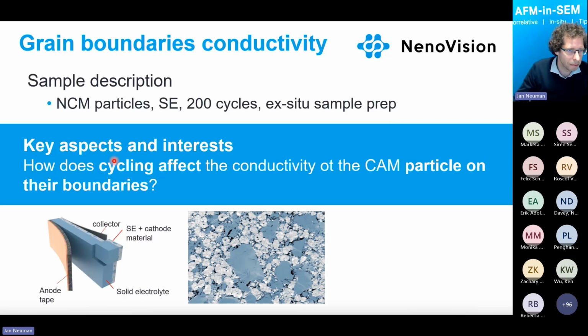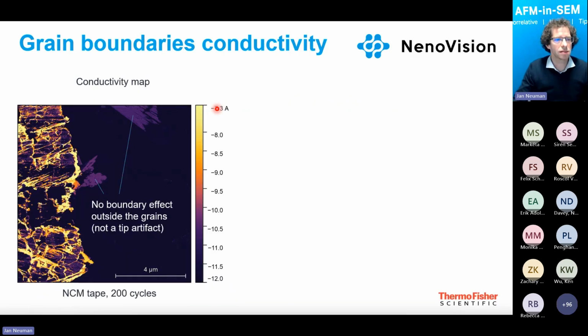This is what you saw before. We use the same samples, NCM particles, solid state electrolyte after 200 cycles. And this is what you see. You can see the conductivity in different areas, but on the cathode materials you see areas which have a significantly higher conductivity. It seems to be on the grain boundaries. One might say it's not an AFM artifact because of the tip interaction on the topography level.